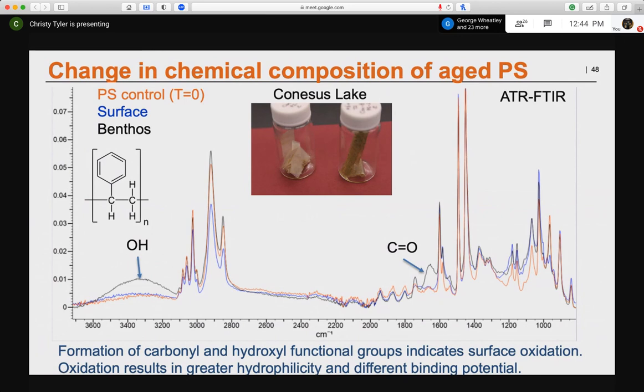I also have a picture of what polystyrene looks like. You can see we have this benzene ring, as well as this backbone, so we have a number of places where oxidation can occur. What we're mostly looking for is whether we're seeing hydroxyl groups, OH, being formed, as well as carbonyls, to indicate the degree of oxidation. The oxidation is going to lead to greater hydrophilicity, so you get more water content under the surface, as well as changing the binding potentials, whether of chemical or microbial.